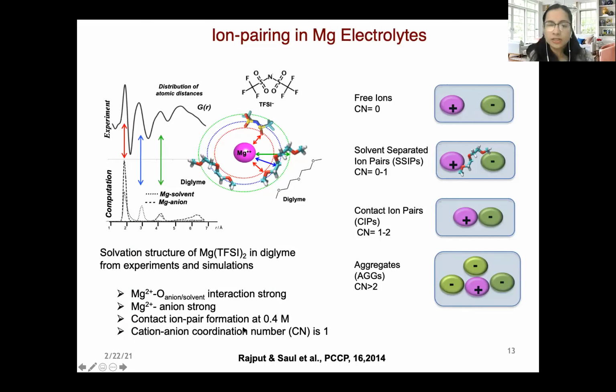Okay, so this information that magnesium TFSI Diglyme solution forms ion pairs even at 0.4 molar was very new and different than what was reported before for lithium ion electrolytes, where we do not see any ion pair formation even up until 1 molar concentration.